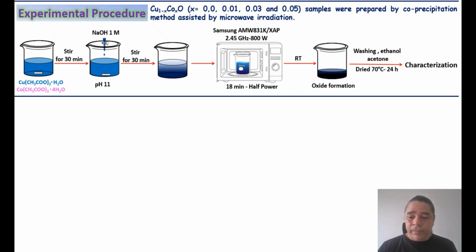Experimental procedure. Cobalt doped copper oxide samples from 0 to 5 molar percentage cobalt were prepared by the precipitation method assisted by microwave radiation. First, copper(II) acetate and cobalt(II) acetate were dissolved in deionized water and mixed for 30 minutes. Then the pH was adjusted to 11, adding sodium hydroxide 1 molar. This solution was stirred for 30 minutes.